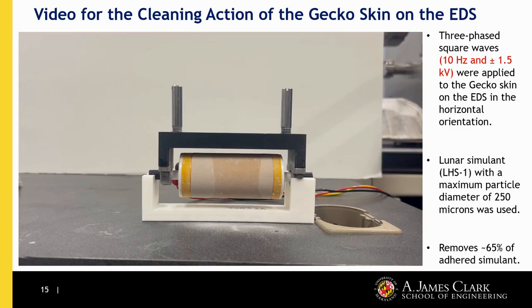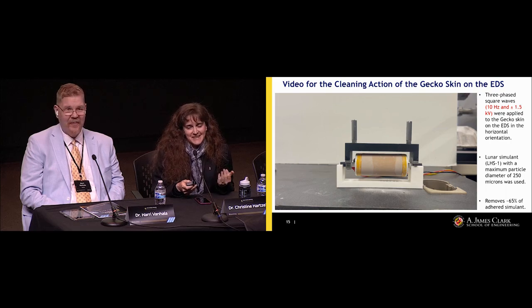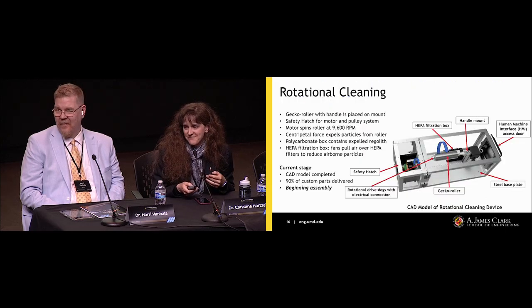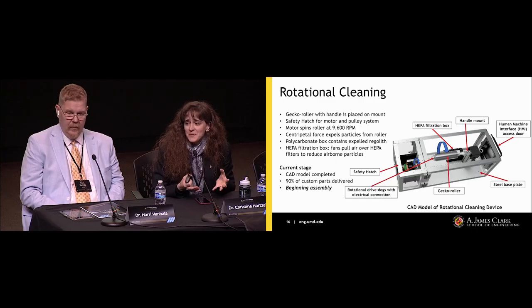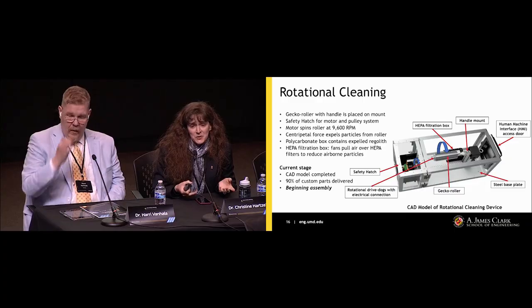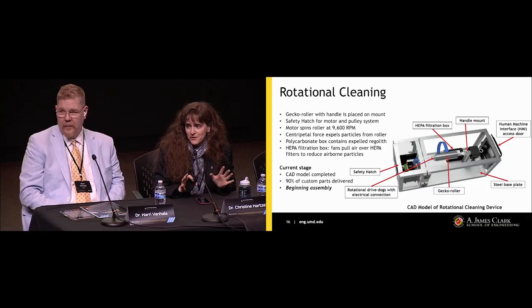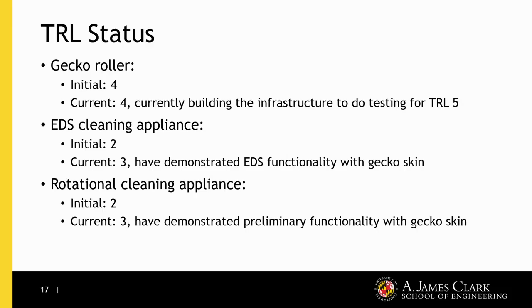So EDS, always very pleasurable to look at, very effective. So it works even when it's embedded underneath a gecko skin. Here's our design for our rotational cleaning test stand. Again, we're just spinning the roller very fast about its axis. And we have this test stand to ensure that our dust will be contained in the appliance. We can control the speed of the roller, and we're making sure that we're not going to be inhaling any of our simulants.